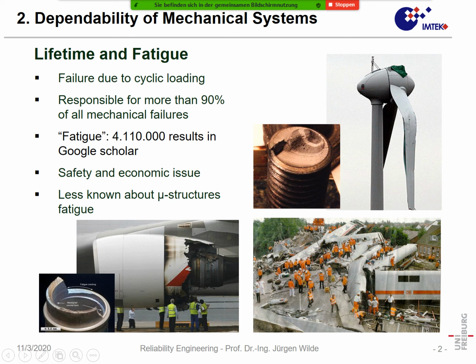Here we see a typical example of such a fatigue failure. A crack started and developed in the part until at some time the crack was so large that the part was weakened very much. And when this part was weakened too strongly, it just broke. So that's a typical event. We have a fatigue failure which grows gradually. We have a small crack, maybe growing at a rate of, let's say, 10 to 100 nanometers per load cycle. But if there are millions of load cycles, it will sum up to millimeters or centimeters, and finally the part is breaking. Here it is a windmill.